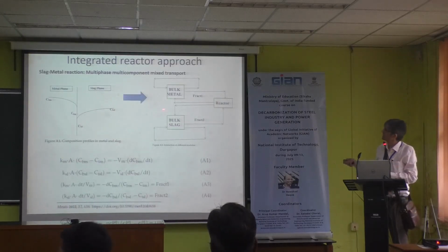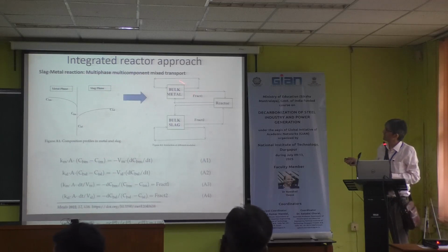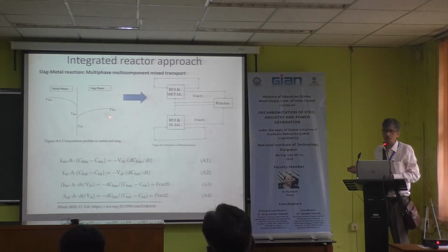So for example, in the integrated reactor approach, this is the example of slag metal reaction. In the slag metal reaction, we know that this is the interface of metal and slag, where there is a concentration gradient existing on both sides, and that is existing because of lack of mixing in either of these two phases. So if the mixing is very good, in a properly mixed reactor, then this bulk concentration should be equal to the interfacial concentration, and both should be in thermodynamic equilibrium in an overall sense. But this is not happening in practice, because